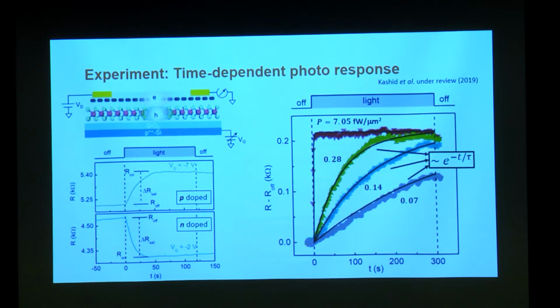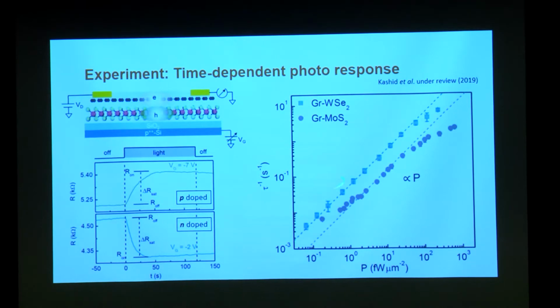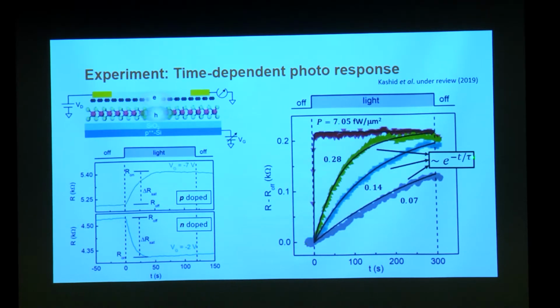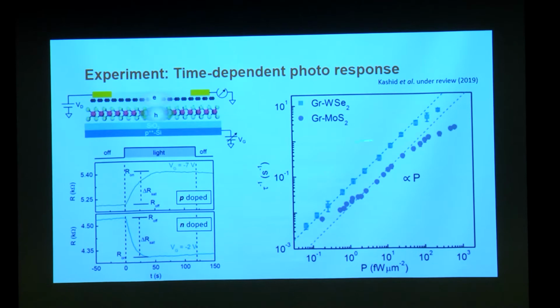Also, each and every one of these relaxations as a function of time is a purely exponential relaxation. So this exponential relaxation time tau is exactly proportional, the rate is proportional to the power of the optical radiation. So what do we have? We have a very slow exponential relaxation process. It's about 12 to 15 orders of magnitude slower than what we think an optical process should be.